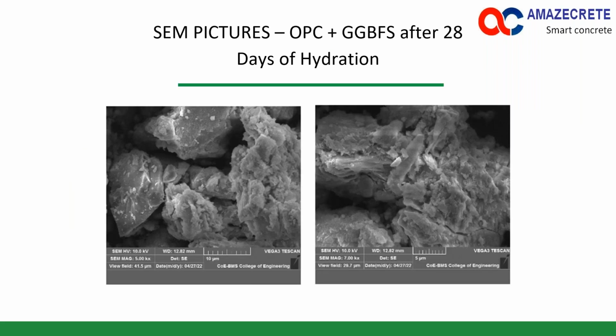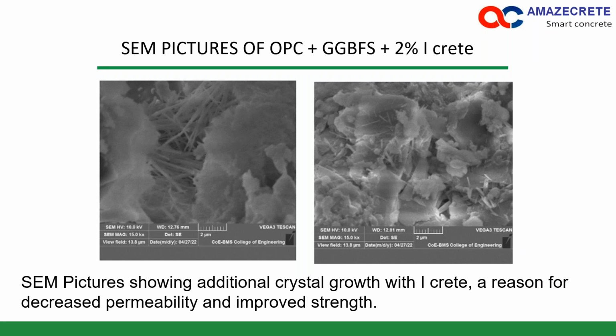So if you look at it, this is actually a blank sample which doesn't contain iCrete. If you look at the spaces in between the grains, you will not see any kind of fibrous structure or crystal growth in between. These grains are more like cubes, or some kind of amorphous structure. But if you look at the next slide, in between the grains you see that these crystals have grown, and on the right side of the pictures, even very small crystals are deposited on the grains of the structure. This is how you differentiate between the one with iCrete and without iCrete. With iCrete, there is a growth of crystals that fills the pores, thereby not allowing the water to enter and strengthening the structure.